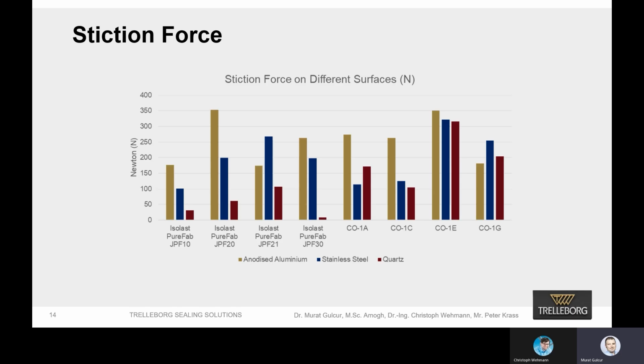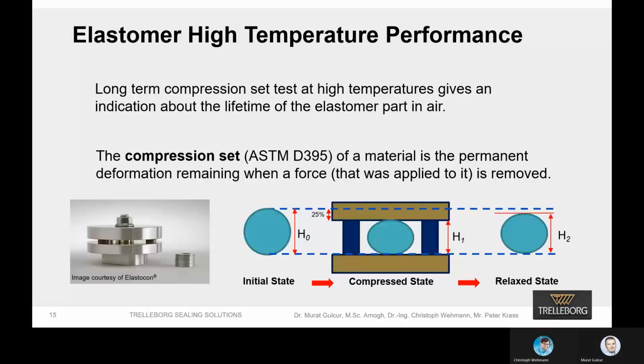Some materials perform with very low stiction force on one surface. For example, JPF30 on a quartz surface, the stiction force is extremely low. We tried this 4 or 5 times, and it always comes out like this. So this material doesn't have affinity to quartz, while it is quite sticky when we do the test on anodized aluminium. Similar to some competitor materials, which all have sticky behavior on every surface. So this also needs to be closely examined when sealing material is specified for an application.